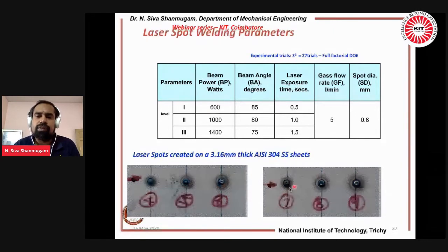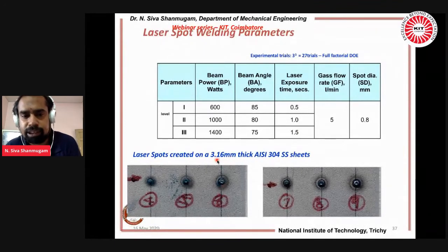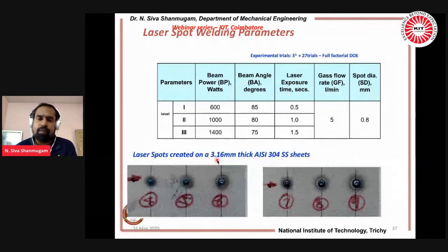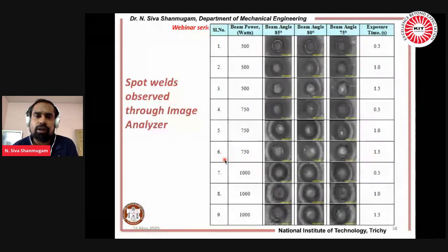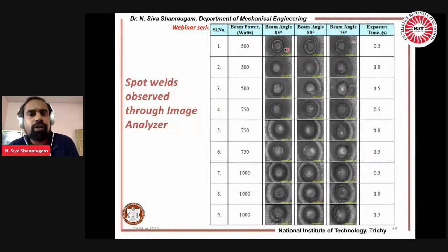This is exposed with different exposure times: 0.5 seconds, 1 second, 1.5 seconds. These are all made on SS304 material. The thickness of the material I selected for the experimentation is 3.16 mm. With a total of 27 trials we have made, you can understand the phenomenon behind laser welding.